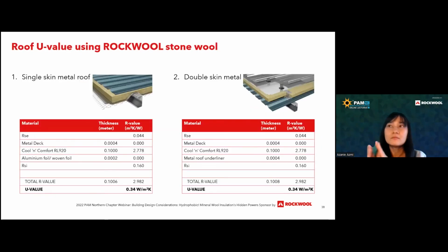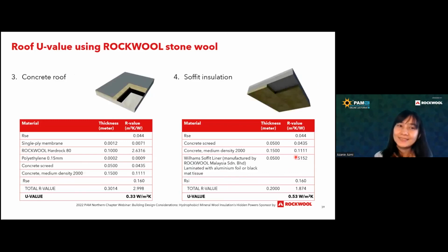U-value, UBBL requirements. These are just examples. What's the thickness that you need to comply with that UBBL requirement? So for a metal roof, you know that it will be below 0.4. To get below 0.4, let's say for a metal roof, you need 100 mm, similar to the double skin. It's around 100 mm or so.